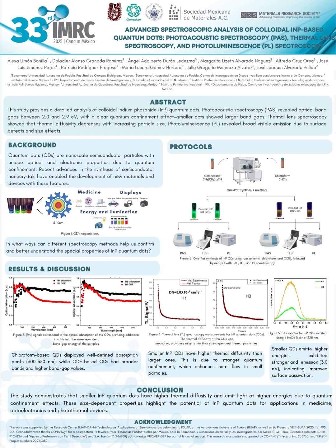However, in samples where the indium phosphide bonds are properly complete, radiative recombination becomes dominant, allowing for a brighter and faster photoluminescence response. In H1, the broader and less intense photoluminescence peaks suggest a higher influence of non-radiative recombination, while in sample number 3, the sharp and intense emission indicates better optical performance.